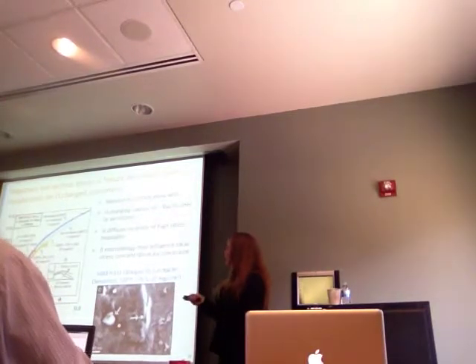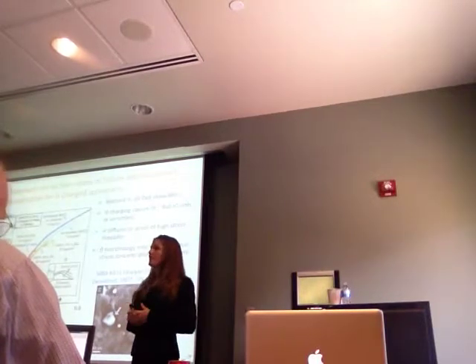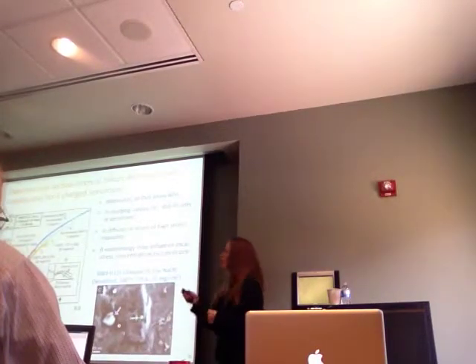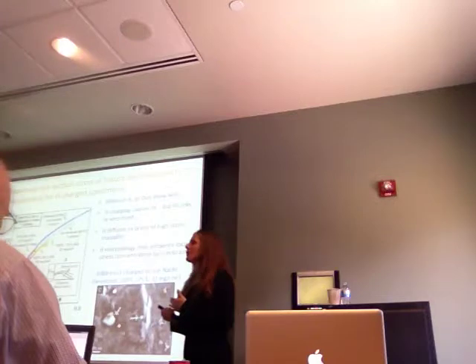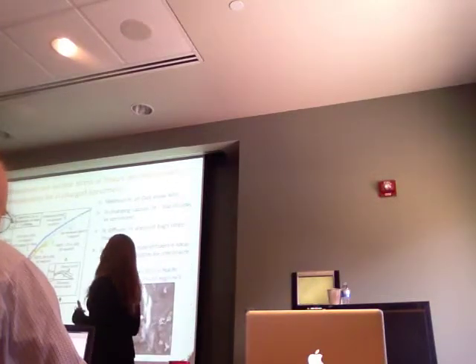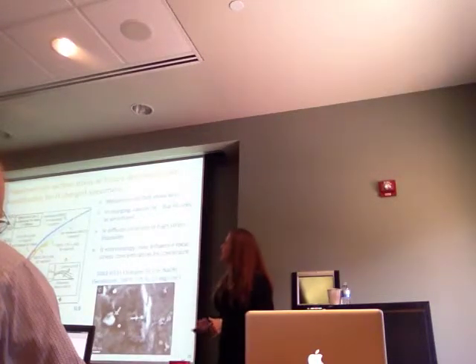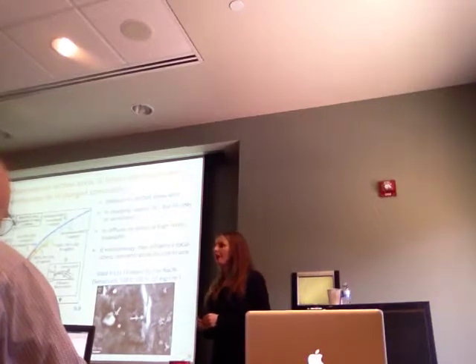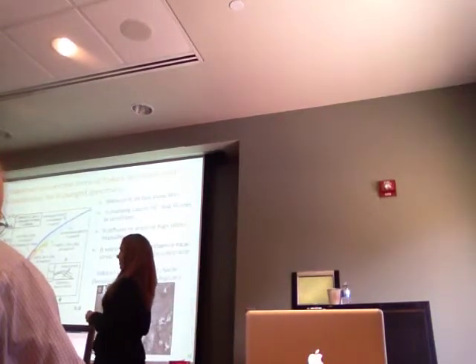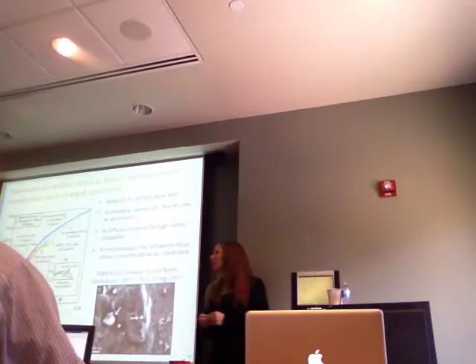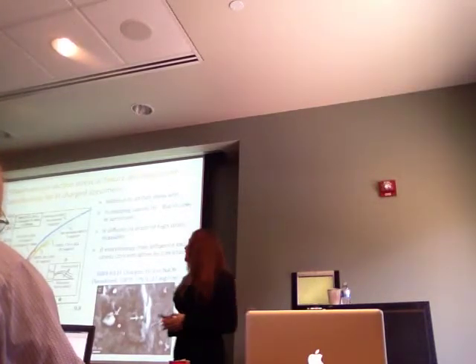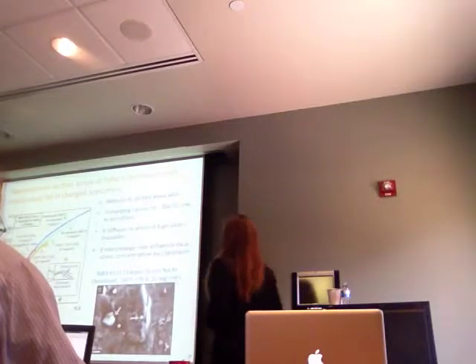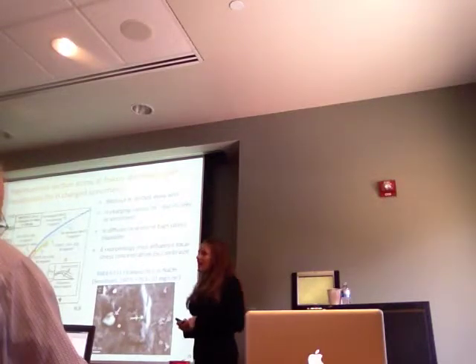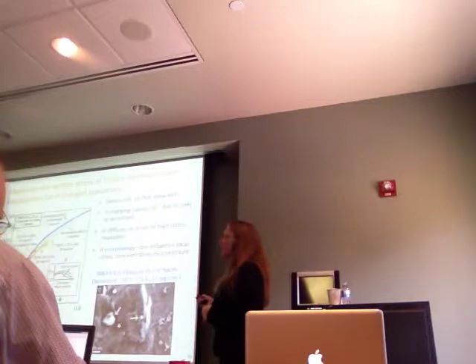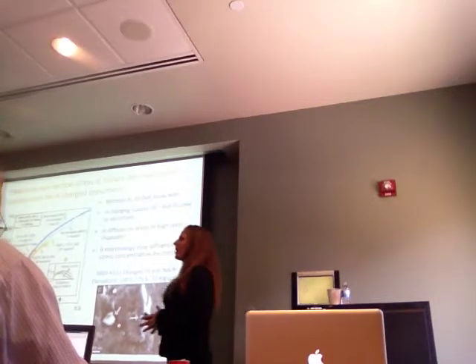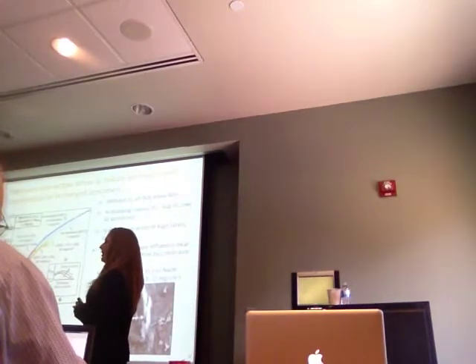So we can absolutely embrittle 5083 with just hydrogen when there's no beta, but this fracture surface is all ductile microvoiding, not intergranular. When you have sensitization, when you have beta on the grain boundaries, you start to see an intergranular fracture. These intergranular regions are very small, but it does fail intergranularly. And this is likely because hydrogen diffuses to the area of high stress triaxiality, and that beta precipitate, just being there, might cause this hydrogen to attract to the grain boundaries.